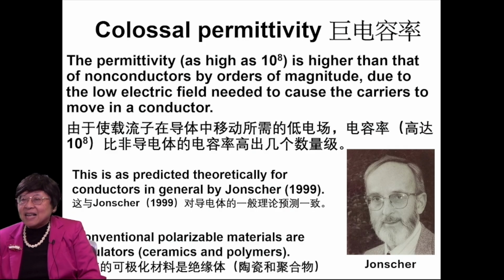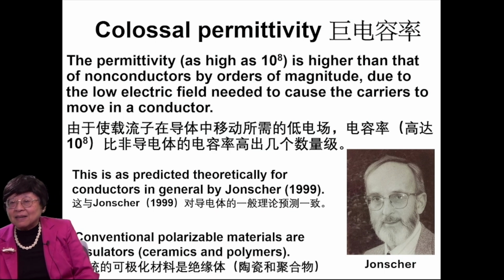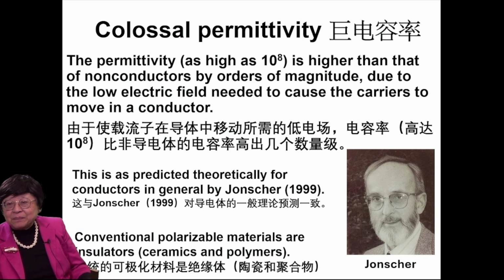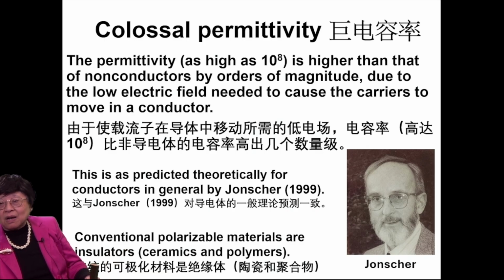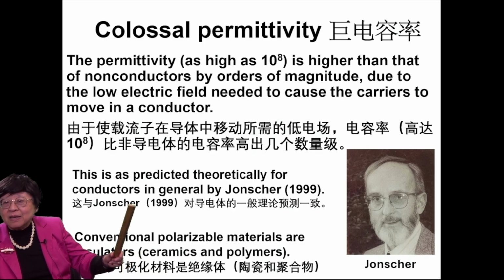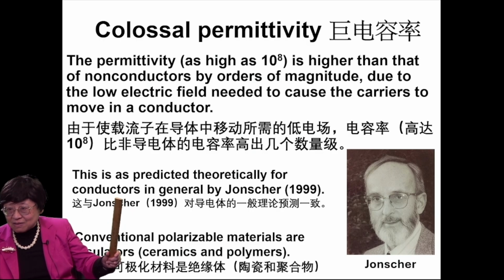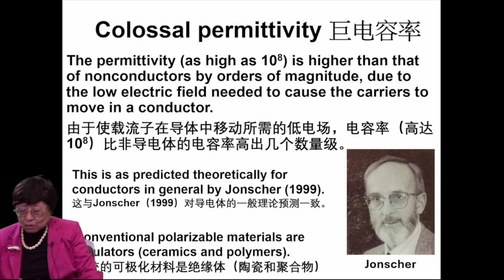The permittivity, as high as 10 to the 8th, as I mentioned, is higher than that of non-conductors, like ceramics or polymers, by orders of magnitude. And that is due to the low electric field needed to cause the carriers, that is electrons, to move in a conductor. And this colossal permittivity actually is as predicted theoretically for conductors in general by Jonscher back in 1999. Now, conventional polarizable materials are insulators, ceramics and polymers. But here I'm talking about conductors, and the conductors exhibit colossal permittivity.